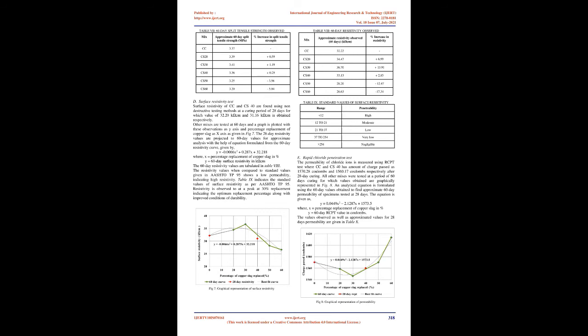The 60-day resistivity values are tabulated in Table 8. The resistivity values, when compared to standard values given in AASHTO TP95, show low permeability, indicating high resistivity. Table 9 indicates the standard values of surface resistivity as per AASHTO TP95. Resistivity is observed to peak at 30% replacement, indicating the optimum replacement percentage along with improved conditions of durability.